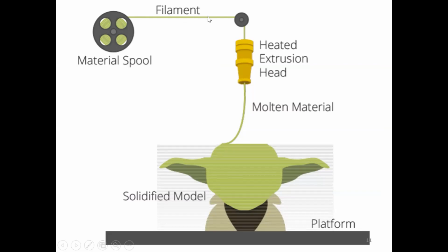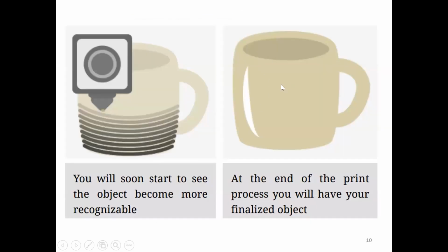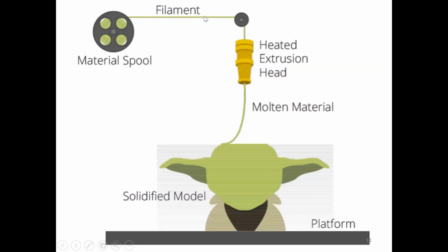So here we need a wire or a filament which will be sent to an extrusion head. Here it gets melted, and through this nozzle it deposits based on whatever CAD model you're going to feed in. These filaments are typically commercially available in 2 diameters, but they need not be the same. Based on your nozzle, you can always change the filament diameter. But in the commercial space, because the machines are available with specific nozzles, we have 1.75 plus minus 50 microns or 2.85 plus minus 50 microns millimeter diameter filaments available. They need not be these. We can always have 5 millimeter or 10 millimeter filament diameter, based on the requirement